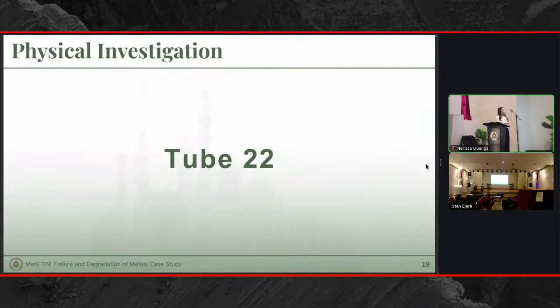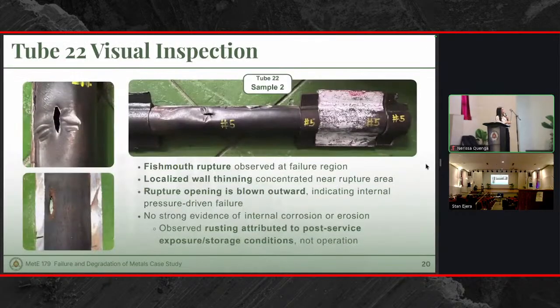Moving on, we also conducted investigation on tube 22, and as you can see from visual inspection, it had a fish mouth rupture, and there was severe localized wall thinning around the ruptured area. These are consistent with mechanisms of short-term overheating, and there is no strong evidence of internal corrosion or erosion, which is consistent with the as-found conditions of the sample, wherein they did not observe any corrosion products present.